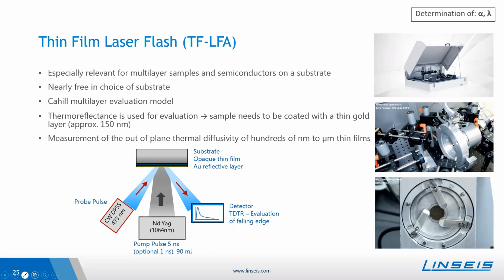The sample preparation is a little bit more complex here, as it is required to put a thin gold layer on top of the sample so that this will be a reflective layer, as the method uses the thermal reflectance of this gold layer to find out the thermal properties of the underlying layers, also using here a multi-layer evaluation model to be able to model all those used layers in the sample.